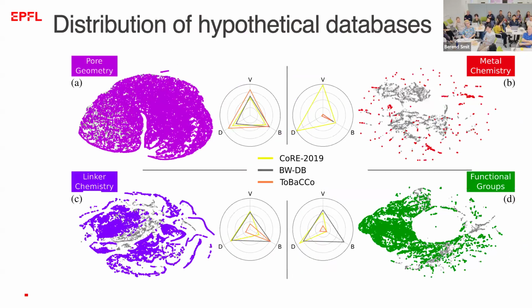So what you then also can do is say, hey, if you look at all the pore geometry, you see we cover it quite well with our hypothetical database. Here you have the linker chemistry. You see you do it a little bit less. Here there are some linkers, the gray dots are the ones that are in the CoRE MOF experimental database. But you see in the metal chemistry, we're really doing very poorly.